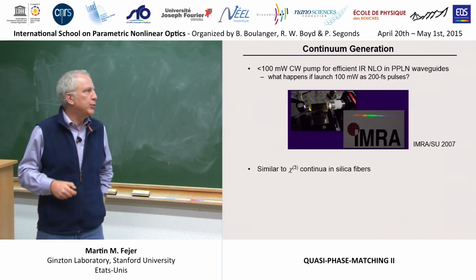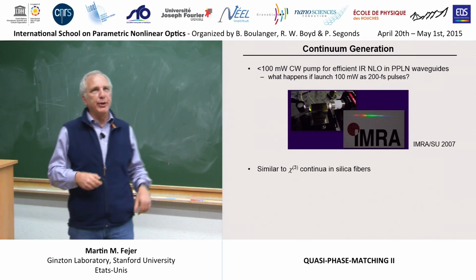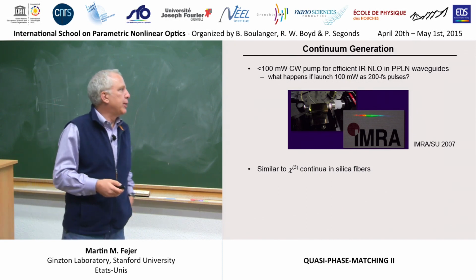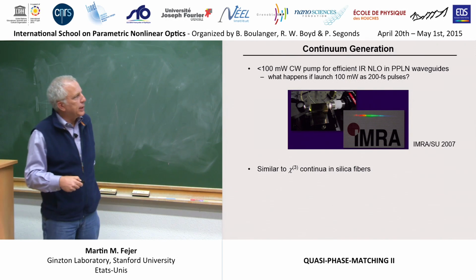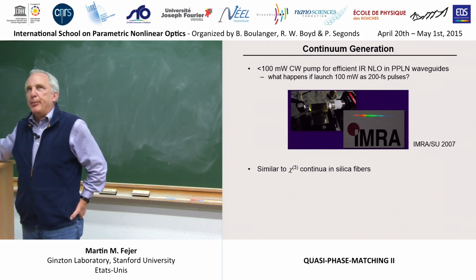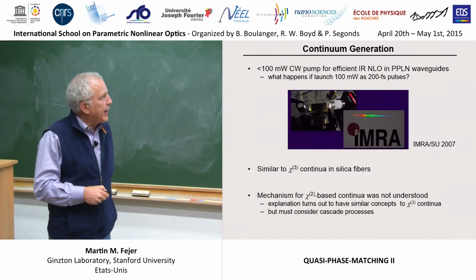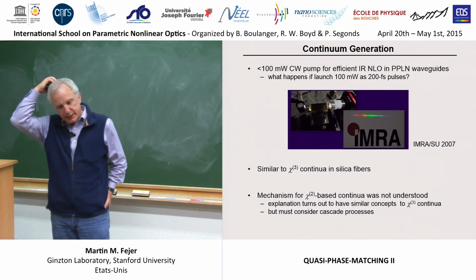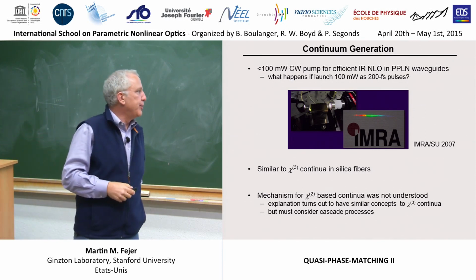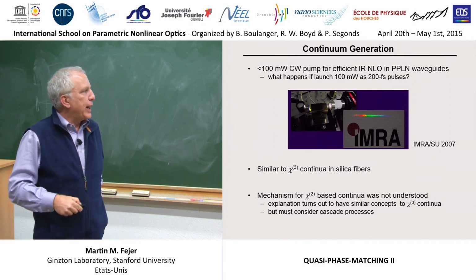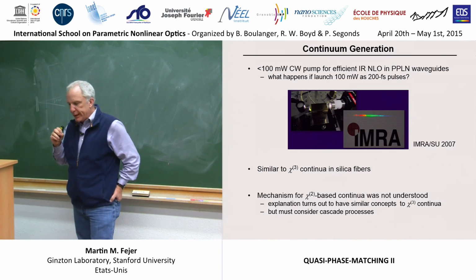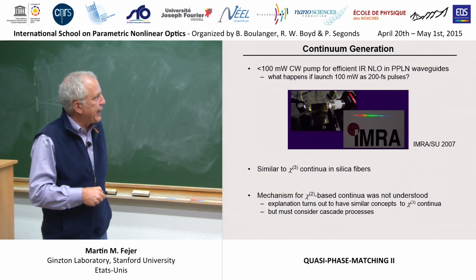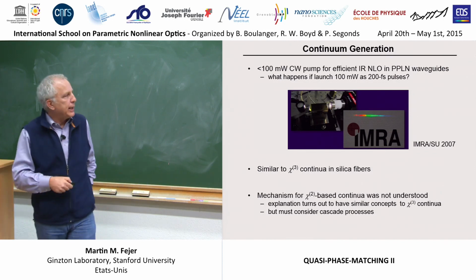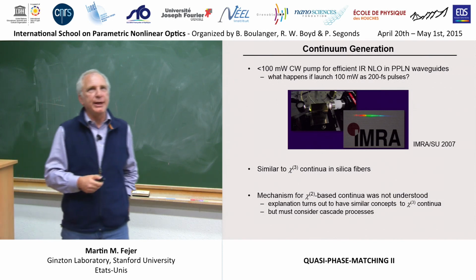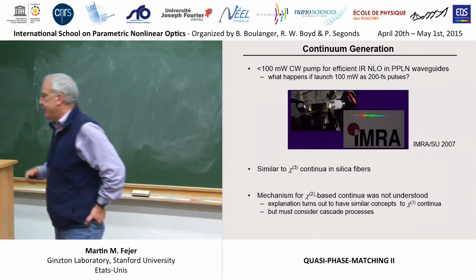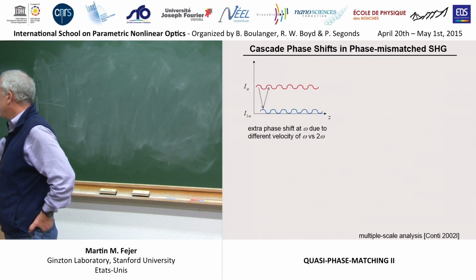This rainbow is a supercontinuum, probably reminding you of ones based on Chi-3 phenomena seen in photonic crystal fibers or other techniques used to build supercontinua based on Chi-3 processes. It was not at all obvious what the mechanism in this Chi-2 medium was for generating a continuum. It turns out the explanation is that it's rather similar to the Chi-3 phenomenology, but instead of the nonlinear phase shift coming from a true Chi-3, it comes from a cascade of two Chi-2 processes, so-called cascade nonlinearities. We need to understand a little bit about those to see how these things work.